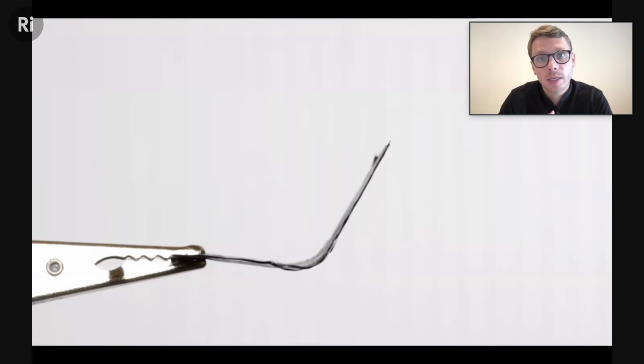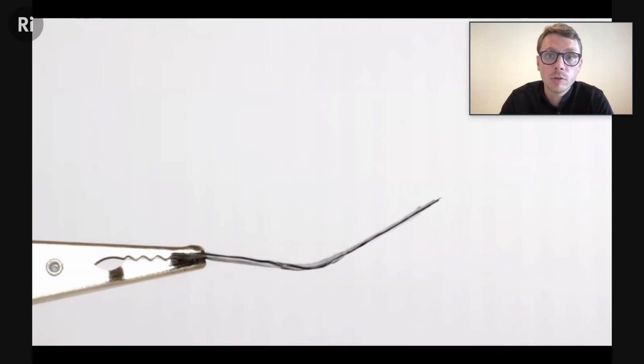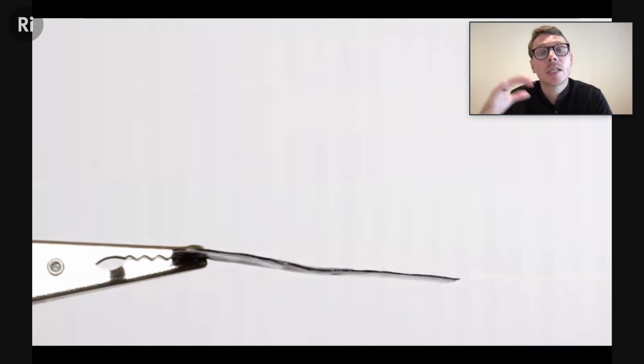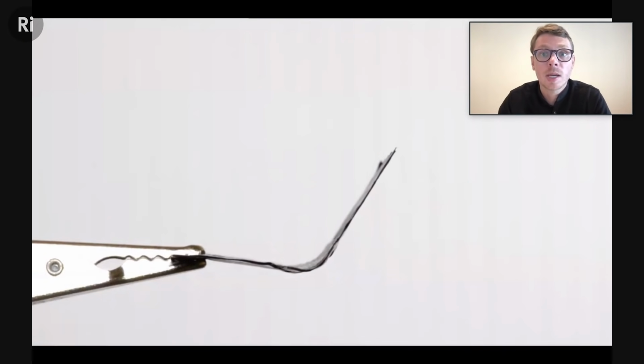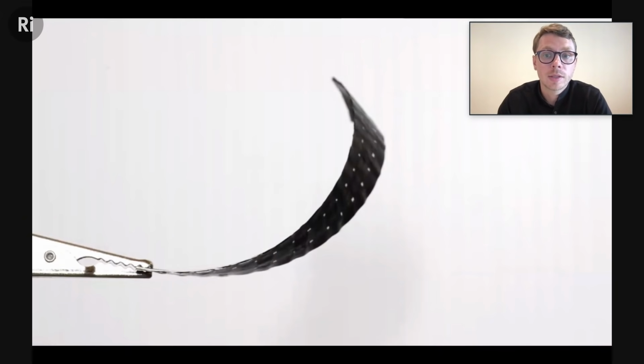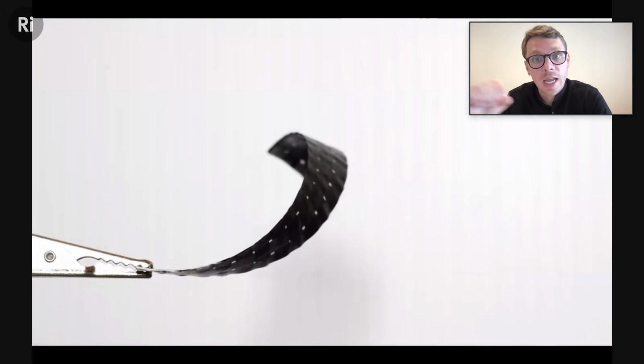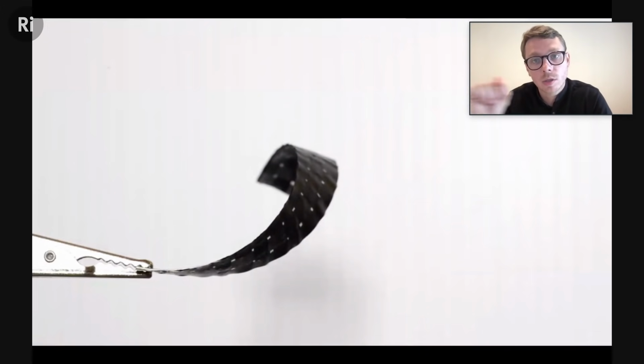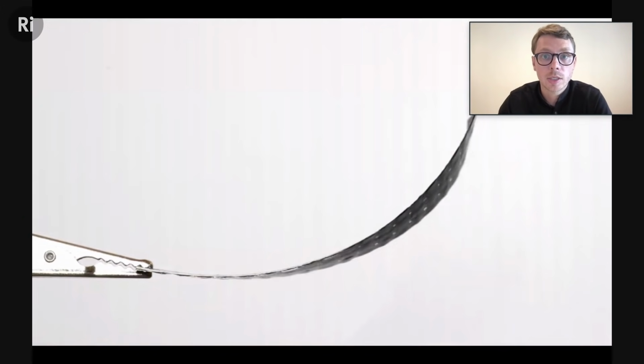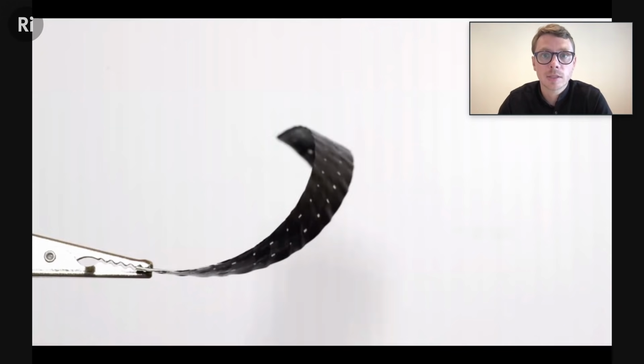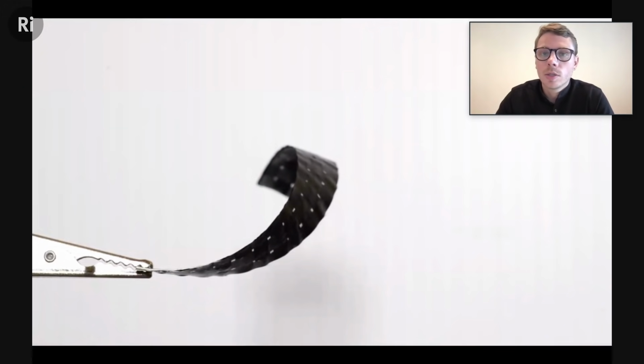And that grain, based on the relationship to the printed polymer and the woven structure of the composite, creates different behaviors when you change the temperature in the environment. So this is carbon fiber that can fold. This is carbon fiber that can twist. And the behavior change is only based on the pattern change that we printed. It's the same exact material composition.